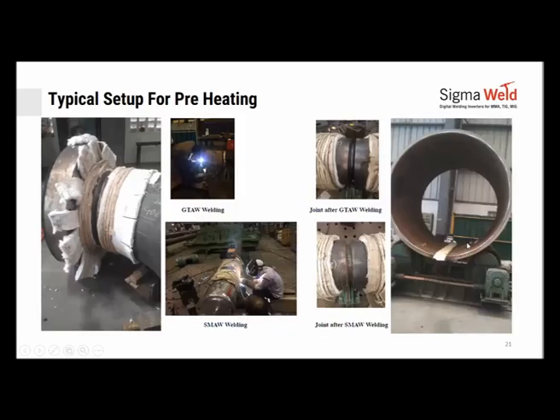Here, similarly, you could see a bigger vessel where a long seam needs to be done. You could have a prefixed blanket like this placed there. Imagine the ease, the blanket never gets hot, right? You place the blanket here, leave it there for 20 minutes. This is a 50 mm thick vessel, if I'm not wrong, 3 meters or 2.5 meters long. This would have heated up in about 20 to 25 minutes, up to 200 degrees. Remove the blanket, start your welding, not a problem.